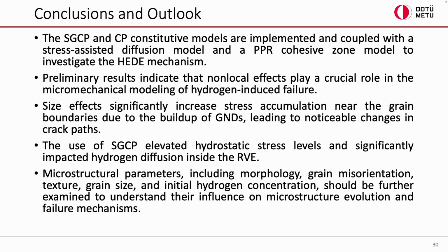Our preliminary results indicated that the non-local effects may play a crucial role in micromechanical modeling of hydrogen-induced failure, as we observed size effects significantly increase the stress accumulation near the grain boundaries because of the build-up of the GNDs, and this changed the crack paths, especially for high hydrogen concentration values.